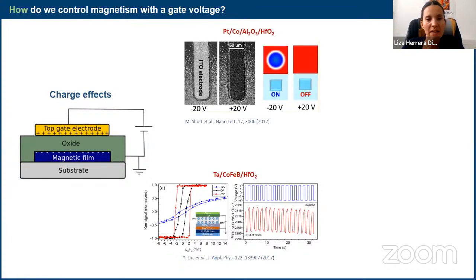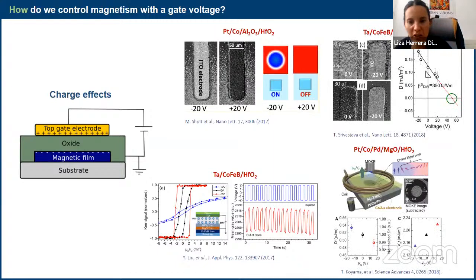with charge effects. So then there are these very nice studies from the several groups in Grenoble. In this study, they could show that they could switch on and off skyrmions in platinum cobalt. And then I said earlier that for DMI, it will be good to be able to bias the bottom interface. However, we know also that DMI depends on the asymmetry between the two interfaces of our magnetic material. So then, in principle, inducing some electrical changes in the top interface can obviously also contribute to a change in the DMI. And this has been measured by also the group in Grenoble and the scientists in Japan. And then they could really see that a modification of the DMI was possible with charge effects.